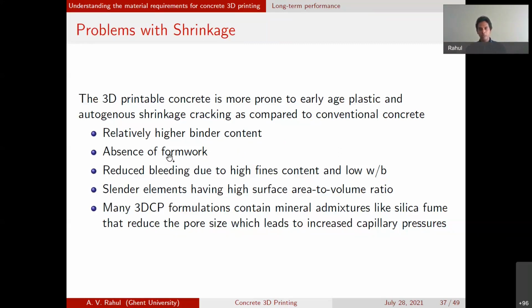But the fact that printed concrete is immediately exposed to the external environment may cause higher early age shrinkage cracking in printable concrete. Then the reduced bleeding and high fines content make it more susceptible again. The other area is the use of slender elements. When you make these architectural elements, you use elements which are very slender with a high surface area to volume ratio. This again is a factor that can contribute to shrinkage.